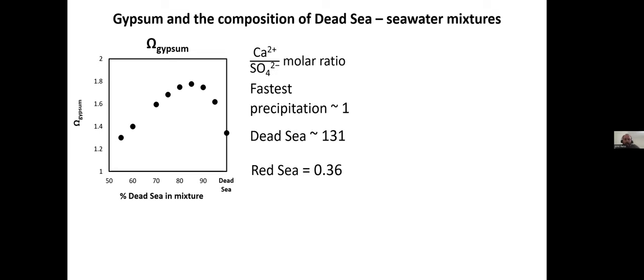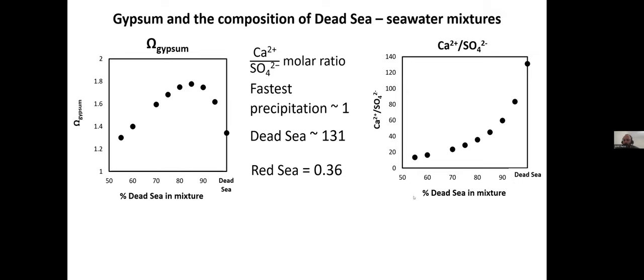Another strong impact is the calcium to sulfate molar ratio. Basically, the fastest kinetics is at a ratio of about 1. The contemporary Dead Sea is over 130. The Red Sea is smaller than unity. So if we look again as a percent of Dead Sea, as the ratio of the calcium to sulfate, we see a small decrease. So again, this favors a much faster precipitation of the mineral.